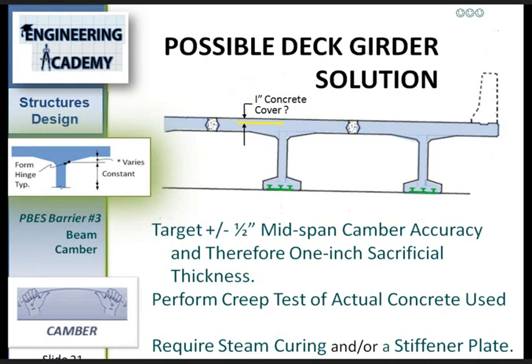Several stiffening steps would likely be necessary, such as requiring steam curing or adding a stiffener plate. At least that's a thought. It is really a question of the benefits of utilizing this sort of deck girder solution versus the added cost associated with overcoming the camber predictability impasse to ensure the deck rideability requirements can be achieved. States that employ steam curing may find these sorts of deck girder solutions more acceptable.